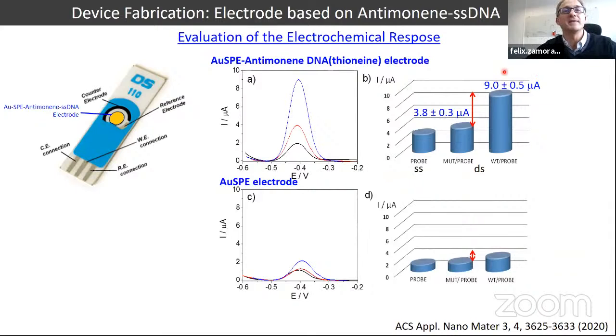So those are the real values. In here you can see that when you use the sequences coming from the people having cancer, we have an electrochemical response corresponding to around 4 microamps. While when you locate on top of our sensor samples coming from people without this problem, you have a rather different electrochemical response, with an intensity around 9 microamps. So it's a big difference. The errors are very small, telling you that this sensor is very effective.